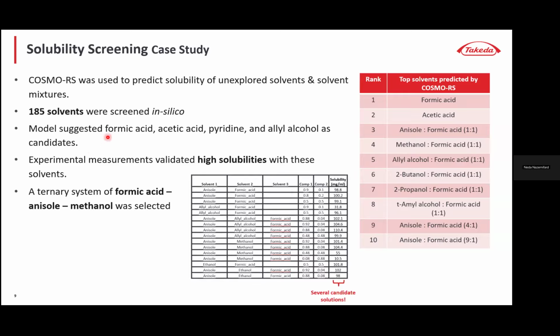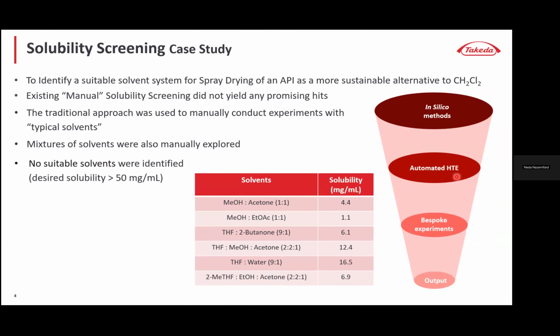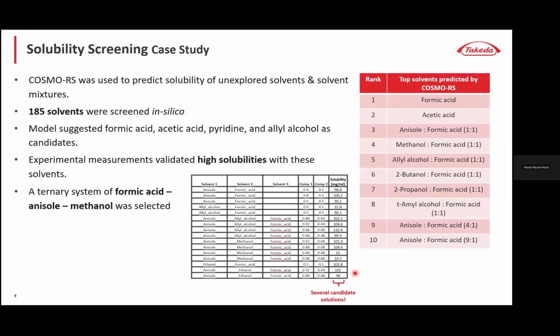So then out of this, we went to the lab and ran some measurements in these solvents in some binary mixtures. We brought this data back to the model and refined the model, and out of that, we had a ternary system of formic acid, anisole, and methanol that was eventually selected out of this loop of, as you can see, the in silico, automated HTE, and bespoke experiments. This is what the project team are using.